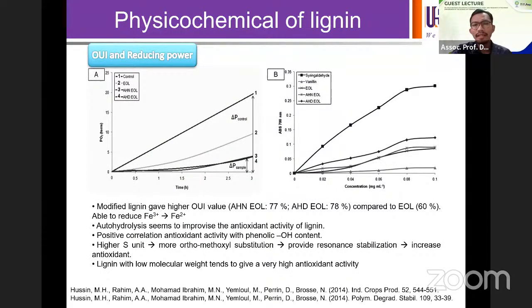And after that, we also looked at the antioxidant activity. So we did oxygen uptake inhibition studies. This was done in France, where this antioxidant assay is slightly interesting because we measure the partial pressure of oxygen produced after we add radicals. So if the antioxidant is good, it wouldn't produce much partial pressure of oxygen. And obviously, when we modify the lignin, it provides a slightly higher oxygen uptake inhibition than without modification. And with the ferric reducing power assay, it was also noted that after the modification of lignin, it provides a better antioxidant activity.